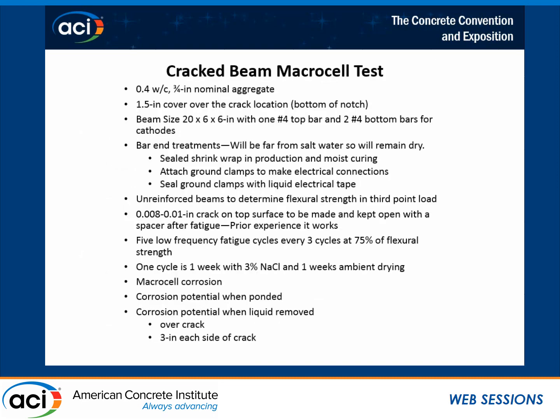The cracked beam macrocell test, as I say, was mainly used for corrosion testing, but you're doing corrosion testing with chloride, so you can learn a little bit about how the chlorides are affecting things. So we had a 0.4 water to cement ratio. If we made beams like this, and in fact smaller beams like this in the lab, they would take years to go into corrosion.